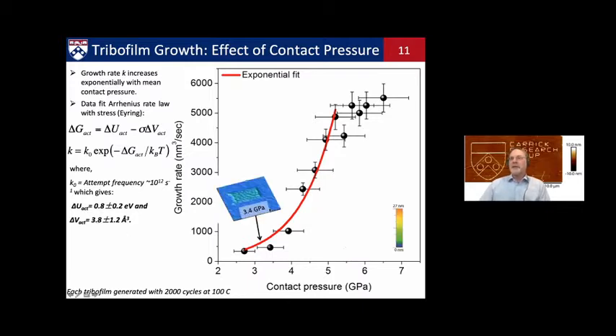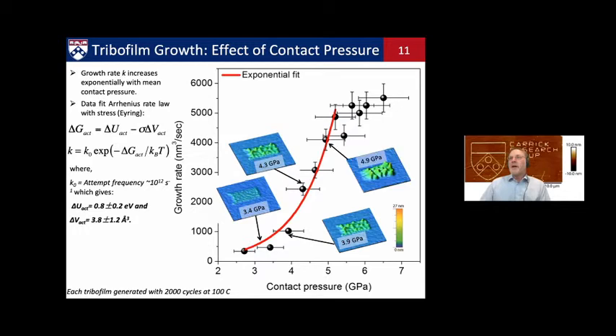And just to show you what this looks like, we're holding all of the conditions constant: temperature, the materials, the concentration, the numbers of cycles. We're just changing the load as we do multiple replicate experiments at different points on the substrate. And what you see is clearly stress leads to a thicker average film. There's also roughness here and topography. So we see a patchiness to the film, just like is known to exist at the macroscopic scale.